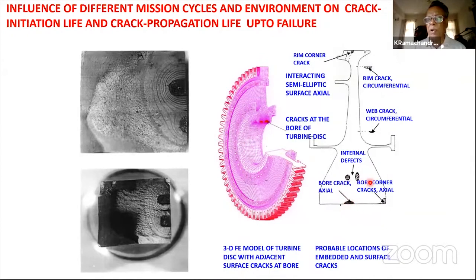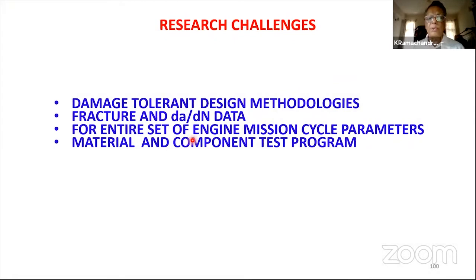It could be cracks in the bore, it could be corner cracks, or defects sitting dormant inside, and they grow. And the way they grow depends on the temperature, the cycles of loading, and maybe there are some cracks which are close to each other. They have a compounding effect. So we should understand the whole fracture mechanics behavior of the system. And therefore, to enable damage tolerant design methodology, we should develop complete fracture and crack propagation data for the entire set of engine mission cycle parameters and for all materials. For example, it could be titanium, it could be Inconel, it could be Udimet, and it could even be some ceramic composites. And it's not enough if you do the material evaluation. We should develop component test data through a component test program, which is sadly missing.